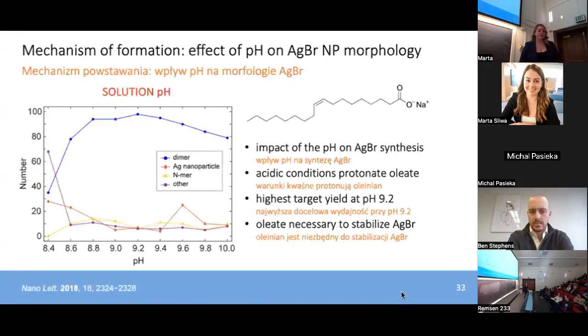So to probe this mechanism, we first wanted to understand and confirm the role of the oleate ligand in our synthesis by looking at the impact of solution pH on the products that we yield. So at acidic conditions, or at pH lower, more acidic than approximately 9.2, which I highlight with this red box here, we see a drop-off in the number of target dimer products, denoted by this blue line.